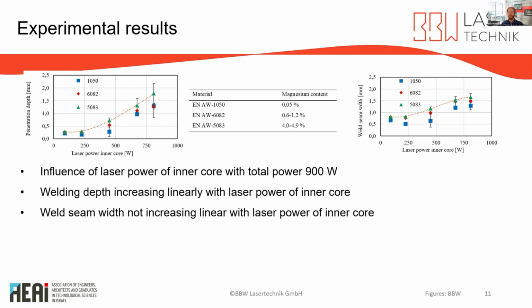We have investigated different aluminum alloys here, and for the alloy AW1050, this is pure aluminum, the process is in the welding regime of conduction mode welding for a laser power of lower than 500 watt, and for alloys AW6082 and 5083, deep welding begins at a laser power of around 400 watt with a deeper penetration for AW5083. The reason for this behavior is the lower evaporation temperature and thermal conductivity for aluminum alloys with a higher content of other elements.